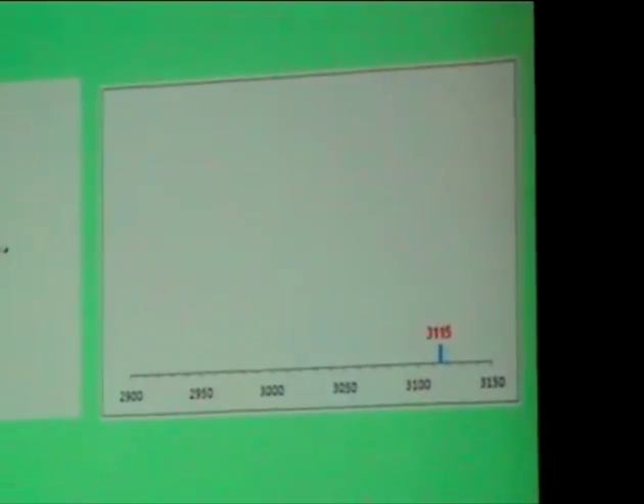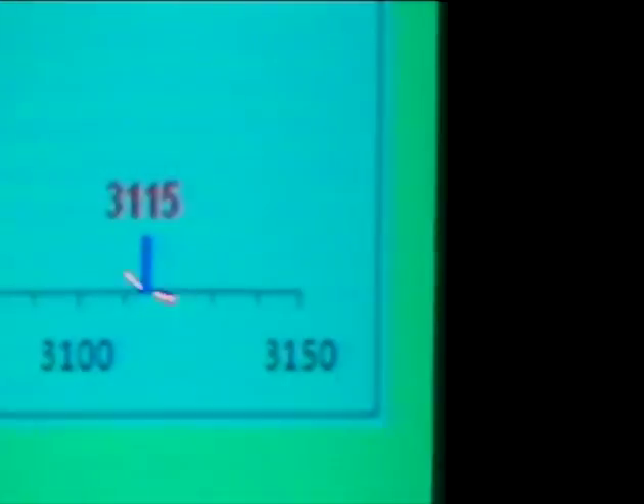Before we make sure we can get this hydrogen-carbon bond, we have to know, if they form the hydrogen-carbon bond, where the FTIR peak is. So first we use DFT calculation to show you where the carbon-hydrogen bond is for the MOF. Before we put the hydrogen in, in the calculation we see between 2,900 wave number and 3,150 wave number, there is a very small absorption peak, between 3,100 and 3,150. There is only one very small peak here. So if you use FTIR without hydrogen absorption, without the carbon-hydrogen bond forming, you should expect only a very small peak in this area.